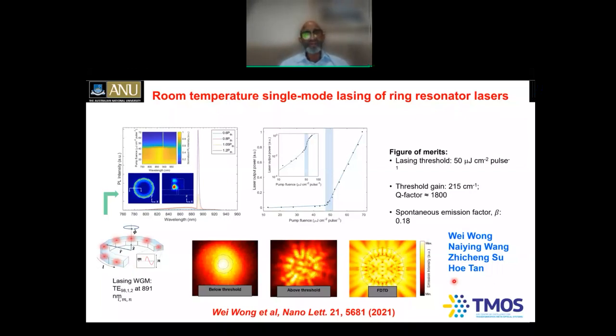Then you can see that he pumps these ones and looks at the light emission. Below threshold, you see a broad light emission like a light emitting diode. Above threshold, you can see the beautiful whispering gallery modes. He compares these with the theoretically simulated ones, and they are very much comparable with each other. Again, narrow linewidth above threshold, S-type behavior, and threshold-like behavior, showing that his hard work paid off. In fact, this work only came out this year, indicating that Wei Wong's hard work has really paid off.